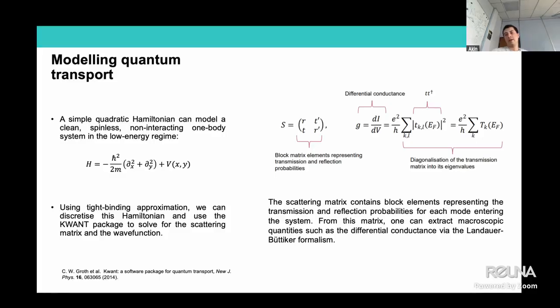So I think the interesting point here is when we talked about modulation to the conductance quantum itself, that was a quantum effect. Whereas here, the quantum itself is being reduced or changed. Whereas when we have impurity or some disorder in the system, we are modulating the transmission probability. And the modulation to the transmission probability can come from various energy or potential structures in the system, which we model here by an arbitrary function, but this can obviously be a quite rigorous self-consistent function as well, which enters the Hamiltonian, and then the scattering system can be solved. Then we can get conductance out of this. So the solution for this is obtained by the open source Python Kwant package.